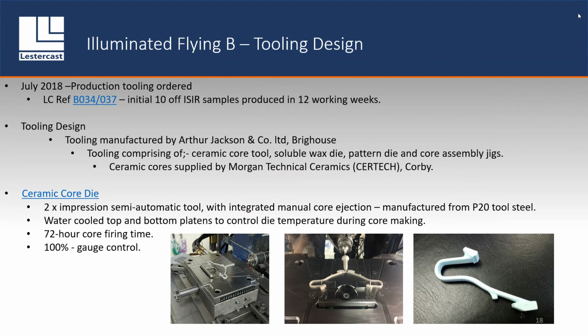Obviously, there was some trials going on, I think, partly some of the trials that were done through Eagle, looking at obviously how to remove the core afterwards, which is something we're going to get to in a second on a later slide. But yes, it's a semi-automatic tool. It's got manual ejection, manufactured from a P20 steel, 72-hour core firing time, and obviously being a key feature, needs 100% gauging as well. So there's some features on here that get gauged once the core's been fired. Those gauges are currently at Morgan's, and we also have a secondary gauge at Lestercast. So we're checking the cores as they're coming in.